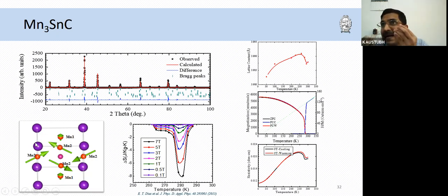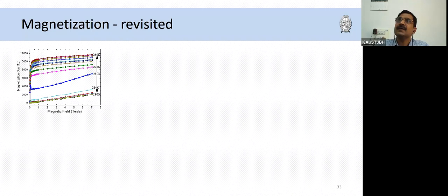So in the manganese sublattice, there were two magnetic manganese atoms, one that carried a ferromagnetic spin and the other that carried antiferromagnetic spins. So how do we reconcile this from EXAFS? So we thought first we should understand the magnetization better, because this itself is very interesting. Within a cubic structure, you have two types of manganese atoms. So we looked at the magnetization very carefully,